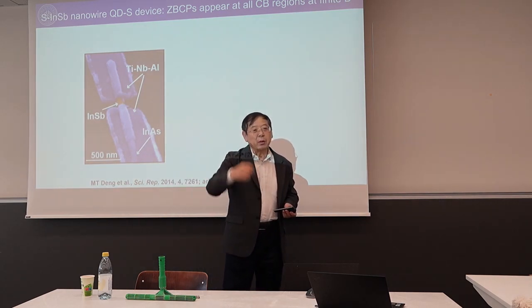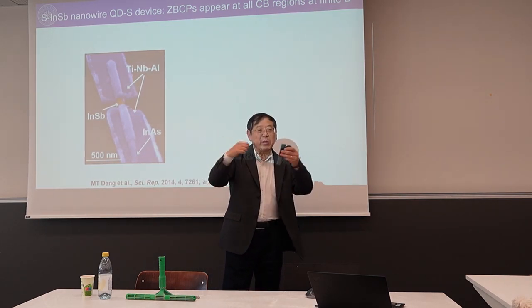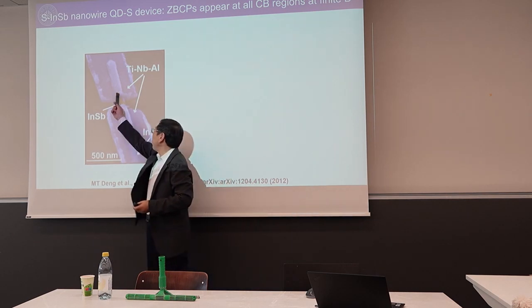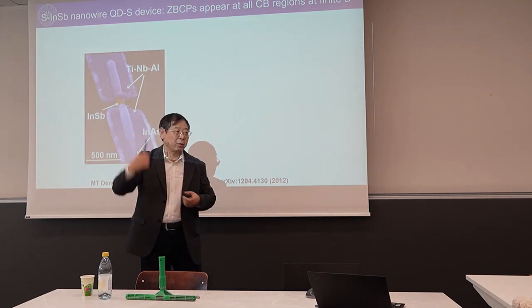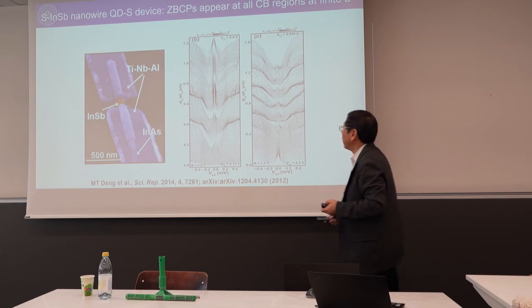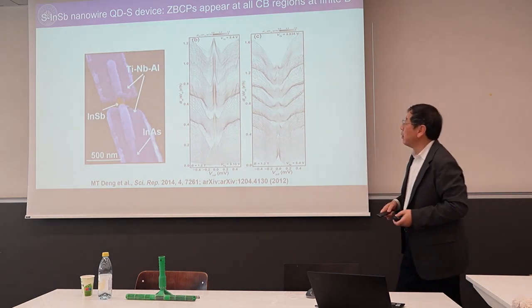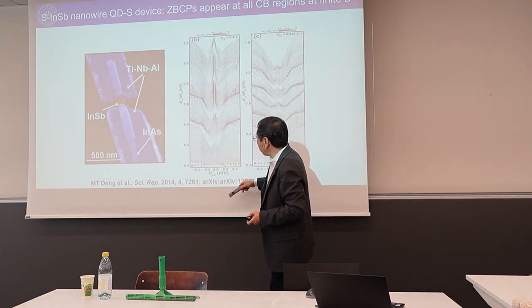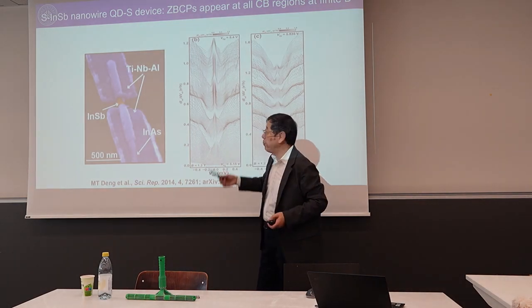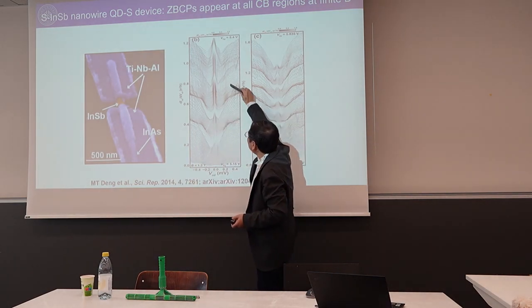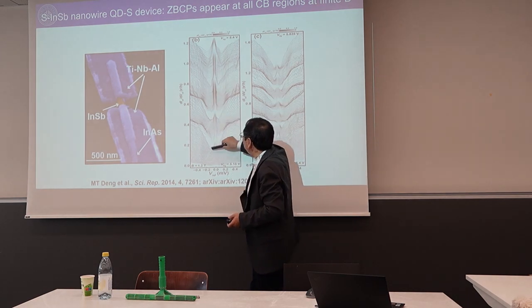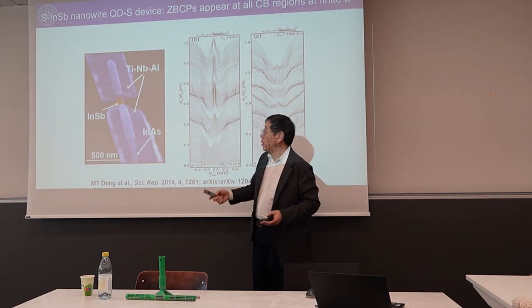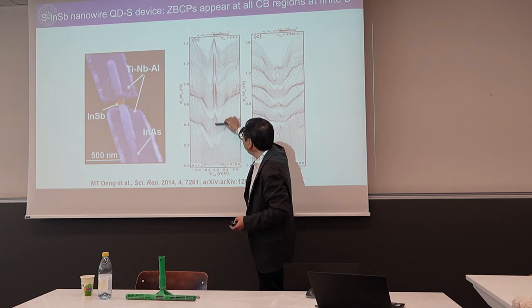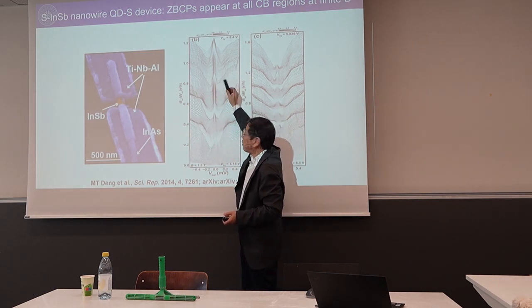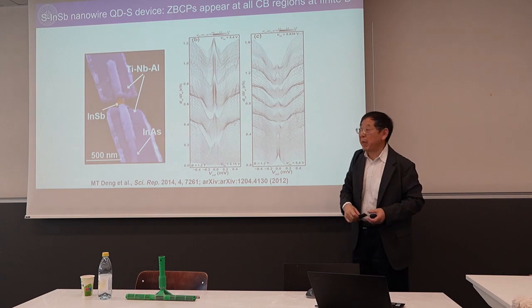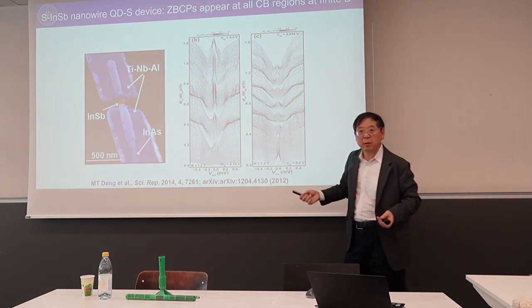Then you can tune the interaction, because when there's resonance, these two Majoranas here and here will interact strongly, so you will see a large separation. This is a spectrum taken. You see it's very nice. These are different lines with different backgate voltage. You see this valley, the valley, which is the superconducting gap. Then in the middle, they go through different Coulomb blockade effects. They show a very nice sharp zero-bias peak, even over a very long gate voltage range.